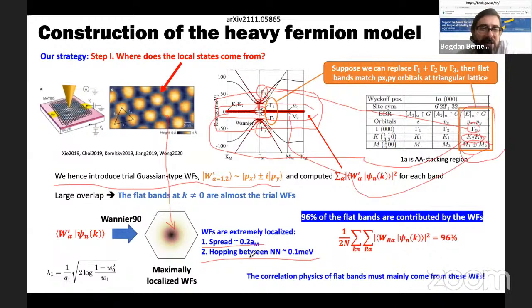Now we know that they cannot describe all of the Bistritzer-MacDonald bands because they have the gamma 3 representation at the gamma point and not the gamma 1, gamma 2 representations. Gamma 3 is two-dimensional, gamma 1 and gamma 2 are both one-dimensional.